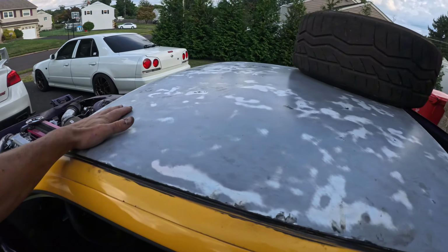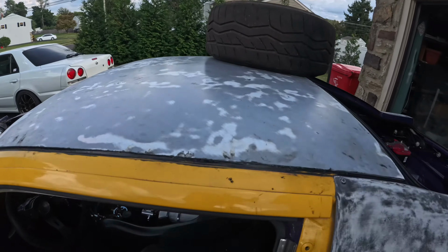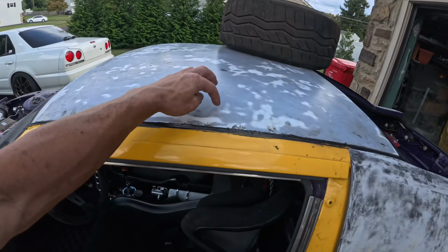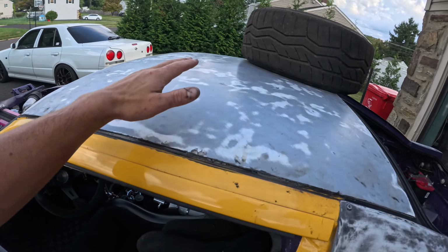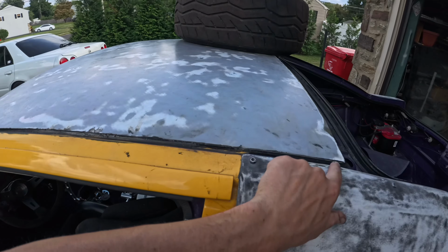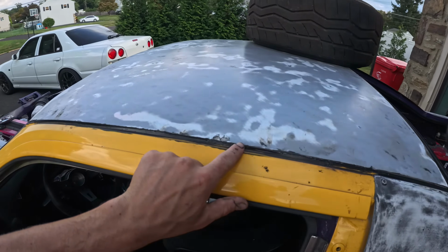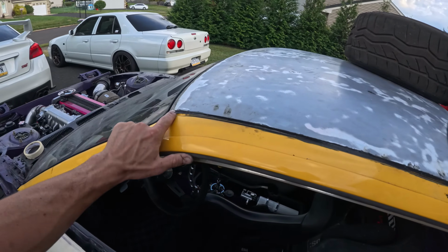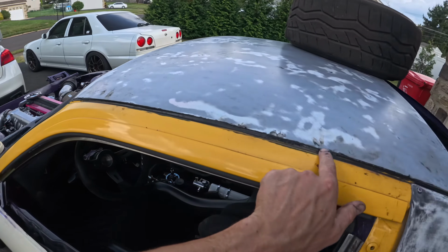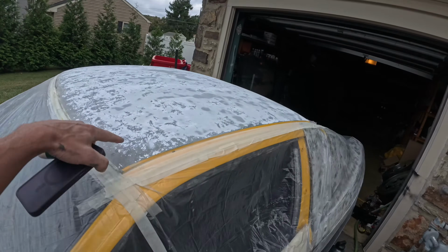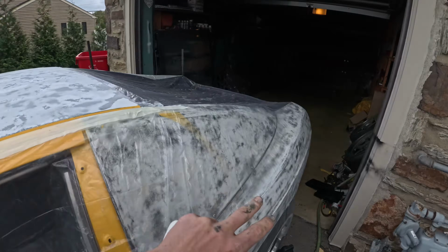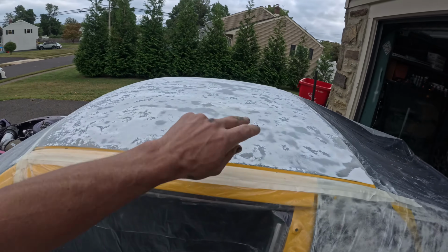Working quickly, I carefully placed the carbon panel on the roof as perfect as possible. Once in the correct position, I clamped it down to secure it and remove any air gaps. Using my fingers, I spread a small amount of the panel bond around the border to ensure any seams or little holes were filled to make molding and blending the panel into the roof easier. After the 6 hours, I removed the clamps and weights from the roof and allowed it to dry overnight.